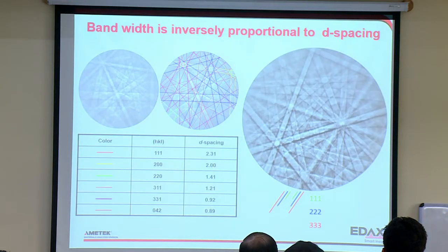So I bring up the d-spacing because of this picture I showed earlier. And so you can see the different orders. And what you know immediately is this is going to be a low index plane, and this big fat one is going to be a high index plane. And there are some in here that are really big planes that, if you look really close, you can see the shadow at one edge here, another edge up here. That's probably a very high index, or a very, very high index plane that's producing that reflection.